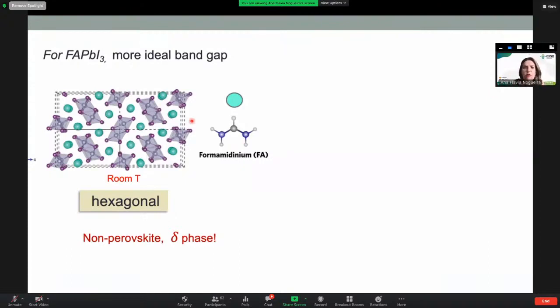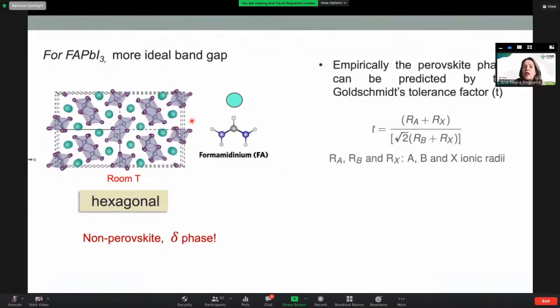Why is it so important? We need to go back to the Goldschmidt tolerance factor, with which we can empirically predict the perovskite phase with some calculations. T is equal to the radius of the A cation plus the radius of the anion X, divided by the square root of 2 times the radius of the B cation plus the radius of X.